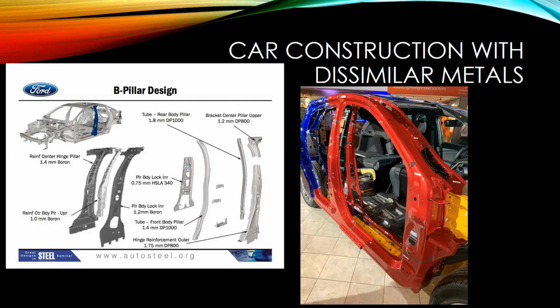And they're called for MIG brazing using pulse spray transfer, as Ace went through, not short circuit. Volkswagen allows either or, but Honda is all spray transfer requirement for all their vehicles. But you have to use silicon bronze in those areas to repair the vehicle properly.